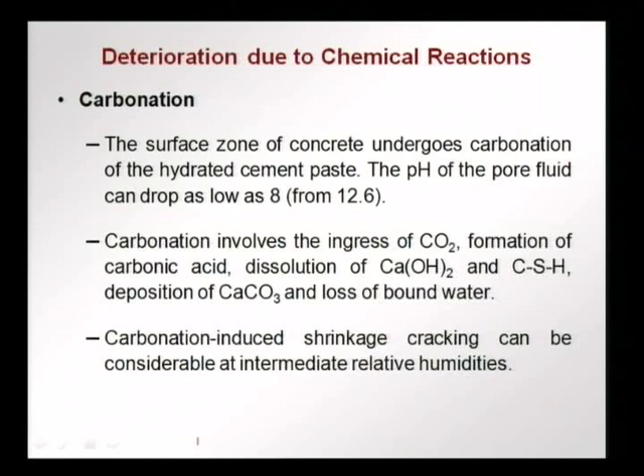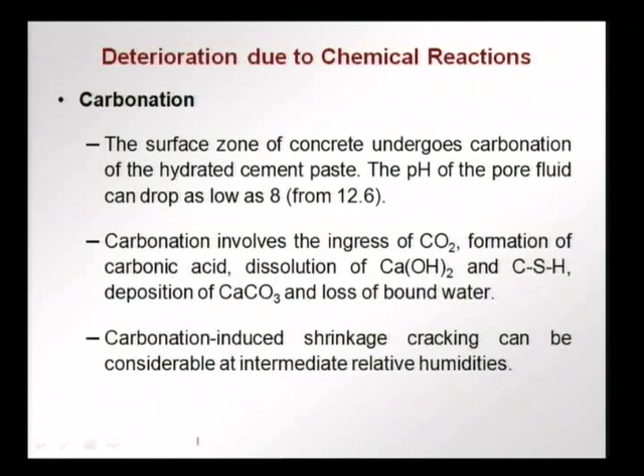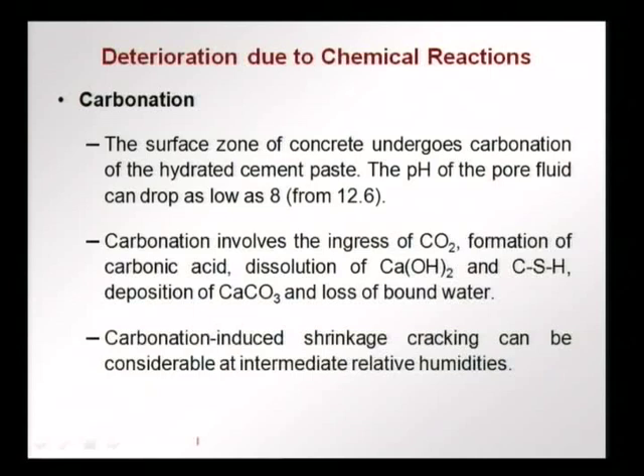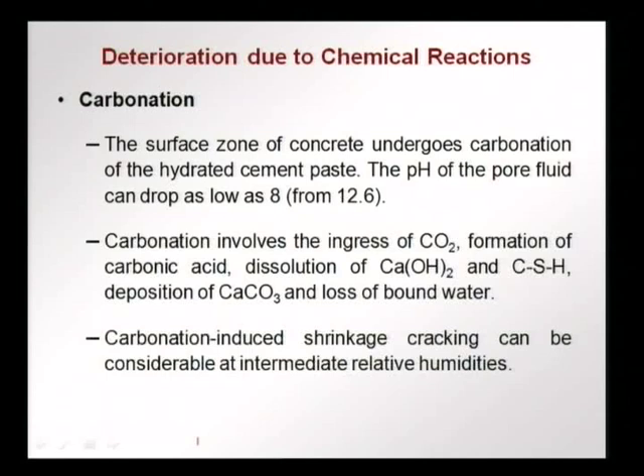Another chemical reaction is carbonation. Carbon dioxide in the air — as mentioned during leaching — enters the concrete and starts reacting with the hydrated cement paste, generally affecting the surface zone. One very important consequence is that the pH of the pore fluid, starting from 12.6, can drop as low as 8. When the pH drops below 11, we can have depassivation of the steel leading to corrosion of the reinforcement. So the change in pH due to carbonation is a very significant effect on durability.